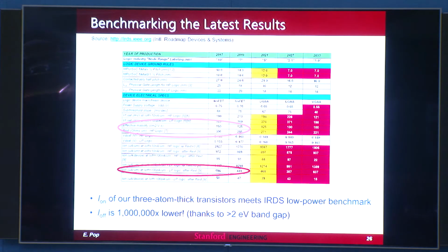And actually, my student Connor, who's done this work recently, went and looked at the ITRS, now it's called the IRDS, the International Roadmap for Devices and Systems. And we're taking a little bit of liberty with this benchmarking, because obviously this is done at slightly lower voltages than what we're doing, and different threshold voltages too. But we are in the ballpark of the requirements for IRDS kind of devices, future technologies, whatever they are, but with a 3-atom thick transistor. And I do want to point out that the off-state currents for this material are actually 1,000,000 times lower than the benchmarks, simply because we have a very large band gap. Silicon has a one-ish eV band gap. We're operating at a 2 eV band gap, roughly. So you can imagine the off-state currents are significantly better than required right now.